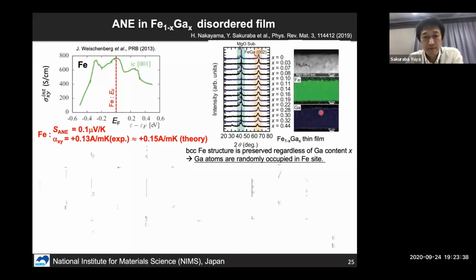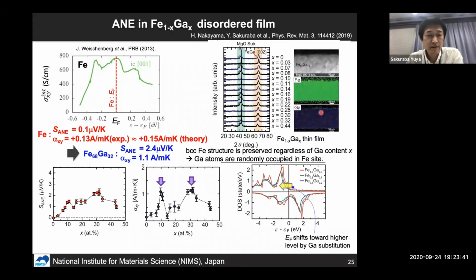Okay, so we measured the anomalous Nernst effect in this iron gallium thin film. As you can see, we successfully observed a large enhancement of the anomalous Nernst effect by adding the gallium. With increasing gallium concentration, the anomalous Nernst thermopower increased, and finally the highest anomalous Nernst thermopower of 2.4 microvolt per Kelvin was observed at this composition ratio.